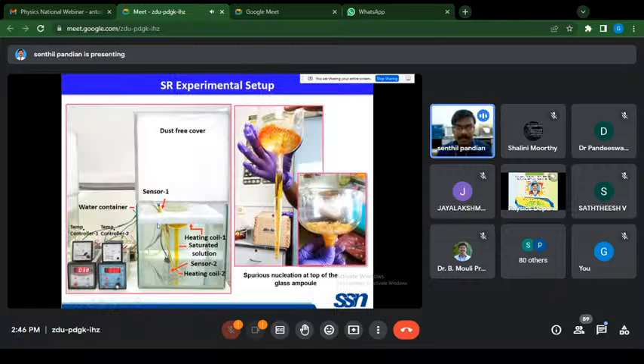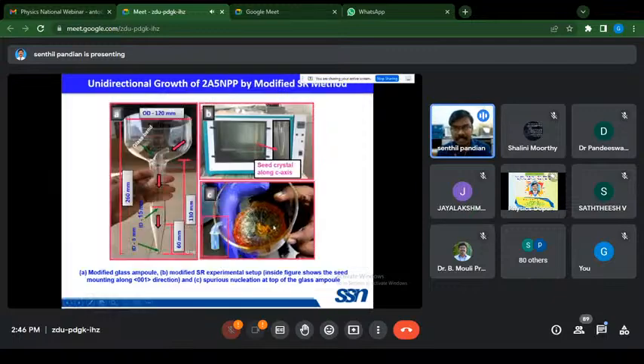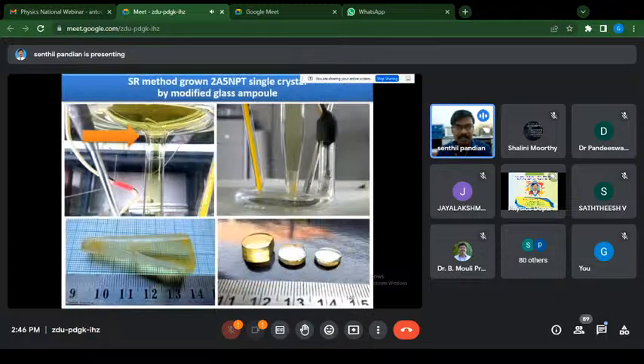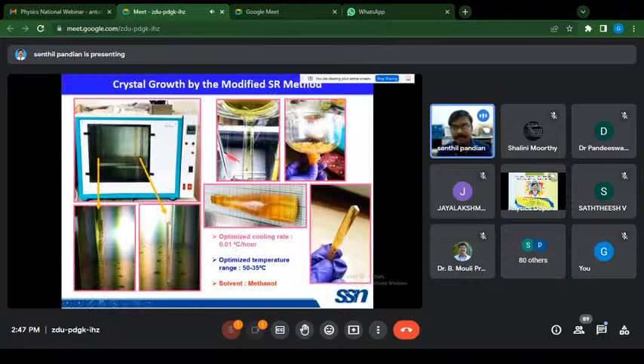And now we are going to see some of the modified SR glass ampoules. When we select solvents like ethanol, methanol or acetone, multinucleation forms at the top of the SR glass ampoule like this. In order to avoid this kind of multinucleation, we have introduced a glass bend like this. So if multinucleation forms, it falls only at the top of the glass ampoule. It will not fall near the crystal and solution interface. And we have successfully grown the SR crystal like this with the modification.